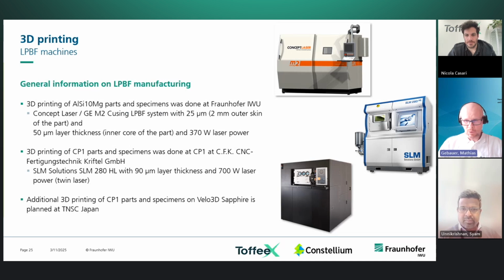I hope most of you are familiar with additive manufacturing and printing. At our institute, we're using laser powder bed fusion as a general term. Different manufacturers have different names for the process. You might hear selective laser melting, laser beam melting, laser fusing. I think one of the machine manufacturers calls it direct metal laser sintering. It's basically the same process. We have a metal powder, in this case Constellium CP1, and we're using a laser to melt this material layer-wise in specific locations to create a three-dimensional part.